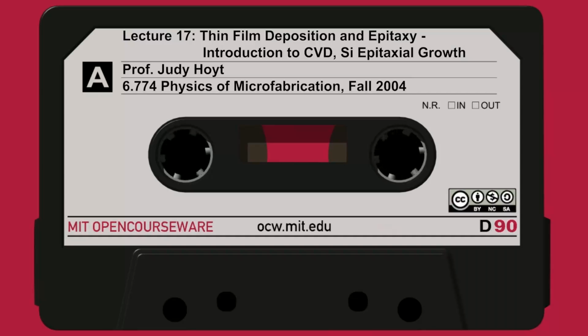So this is equation 8. I just repeated exactly that same equation we just saw for the deposition rate. And you notice because of the way these add here, the deposition rate is going to be determined by the smaller of the two, K sub S or Hg. So let's say K sub S is very small. Then I can ignore it in the denominator, and then the Hg's go out. In that case, the velocity just depends on K sub S times this concentration.